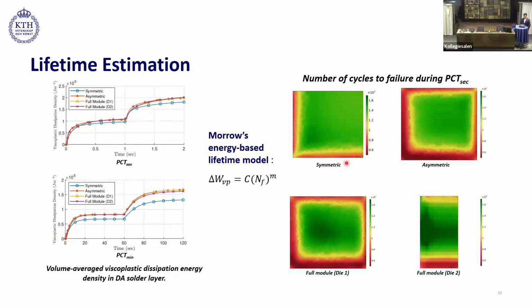in all the cases, we see that the solder material experiences lower number of cycles to failure around the edges, like here and then here, which is represented by red and dark red color. We see that the symmetric power module exhibits higher number of cycles to failure in comparison to the asymmetric and the full module. And in these regions, they have the minimum number of cycles to failure. Plus, in this region, in the full module, the number of cycles to failure also reduced because of the presence of parallel die.